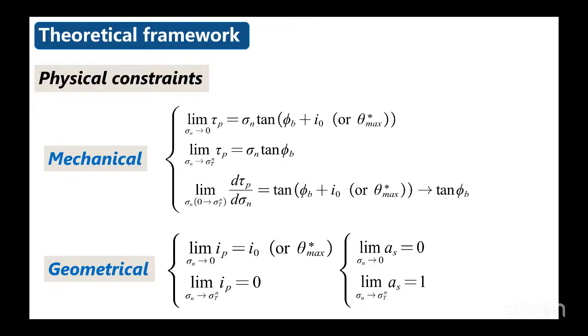The proposed theoretical framework strictly satisfies the physical constraints of a rough rock joint subject to different magnitudes of shearing. From the mechanical viewpoint, when the normal stress is nearly zero, there is no asperity damage, and thus the total friction angle is the highest. As the normal stress grows to the transitional normal stress, a very high normal stress level, the total friction angle decreases continuously to the basic or residual friction angle, which is a constant. During this normal stress change, the dilation angle declines from the maximum at the initial asperity angle to 0, and the shear-off ratio grows accordingly from 0 to 1.